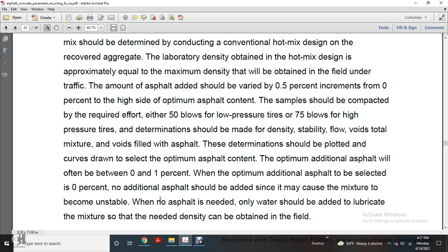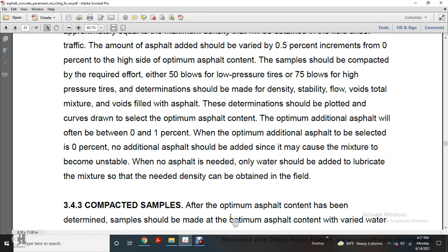Optimum additional asphalt will often be between 0 and 1%. If the optimum additional asphalt is 0%, no additional asphalt should be added, since it may cause the mixture to become unstable. No asphalt is needed. Only water should be added to lubricate the mixture to achieve the density that can be obtained in the field.